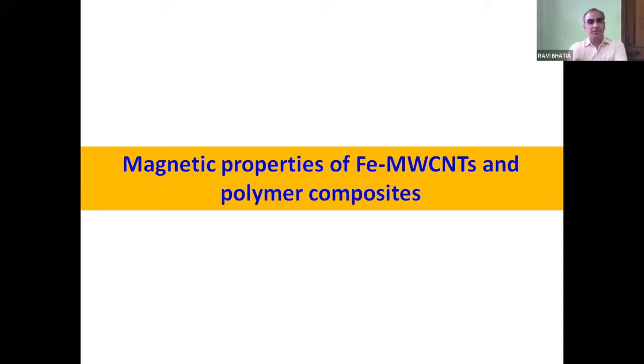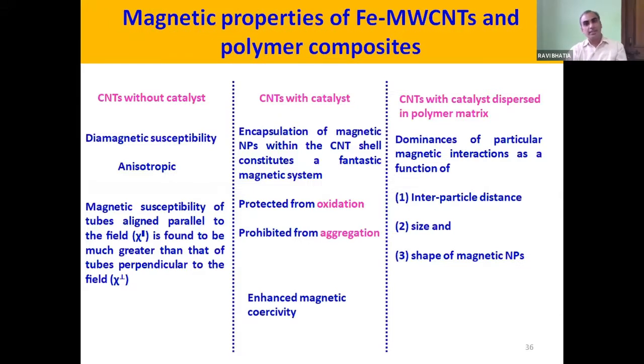So we had observed the encapsulation of iron nanoparticles in terms of nanorolls in the carbon nanotubes. We use the same carbon nanotubes for the fabrication of polymer composites, and we try to assess the magnetic properties of this system. Before we go to the measurement part of it, CNTs show a diamagnetic susceptibility which is anisotropic in nature when there is no catalytic particle within it, because it is carbon material. Carbon should show a diamagnetic susceptibility.